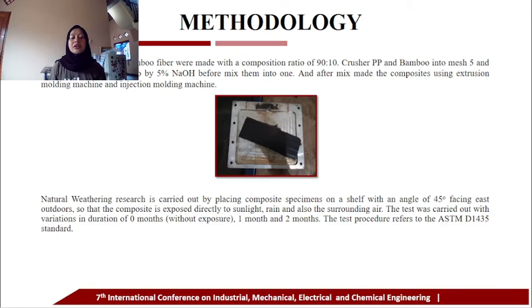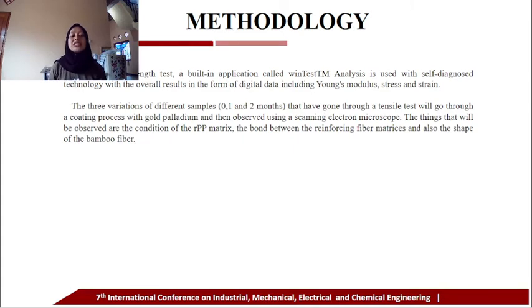Natural weathering research is carried out by placing composite specimens on a shelf with an angle of 45° facing east outdoors, so that the composite is exposed directly to sunlight, rain, and also the surrounding air. The test was carried out with variations in duration of 0 months or without exposure, 1 month, and 2 months. The test procedures refer to the ASTM D1435 standard.